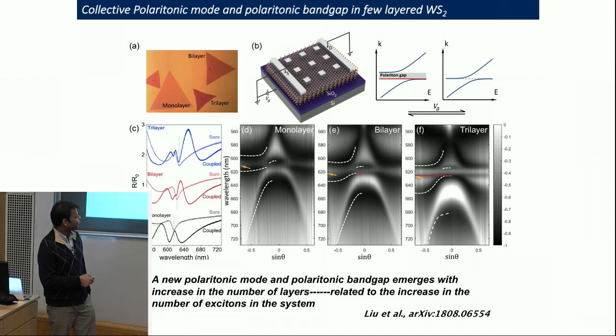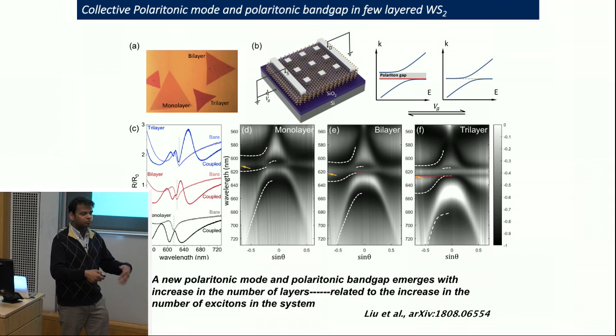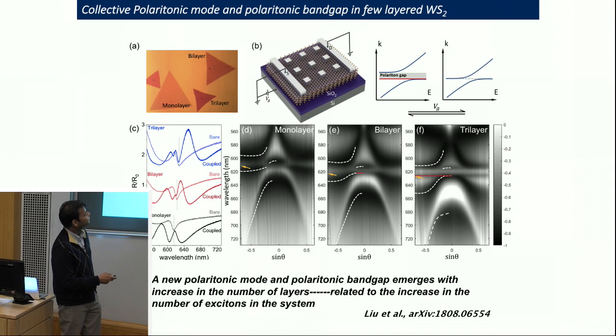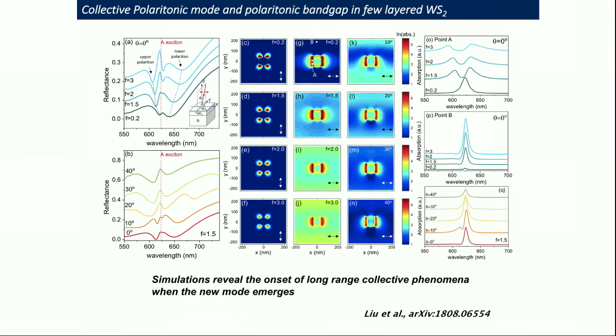But this clearly is a function of the number of excitons that we are creating in the system. So we started to do some simulations, typically COMSOL or finite difference time domain simulations. Those of you who deal with FDTD know they don't give you any microscopic information, but they at least tell you something. That something was that we could reproduce these features using FDTD simulations by increasing the number of monolayers in the system, and that we can do because we can measure the reflectance. From reflectance, we can get the dielectric dispersion, feed it into the system, and extract all those things. So we started to look systematically at what is happening.